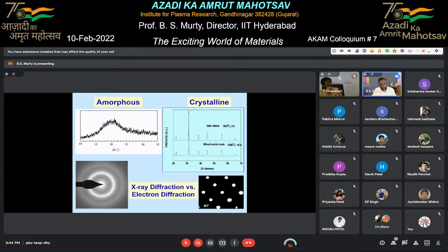And if you do the same thing with a transmission electron microscope, you get what is called a diffused ring. And the moment you see a diffused ring in a TEM, and a broad peak in an XRD, you clearly say, oh, this material is amorphous.